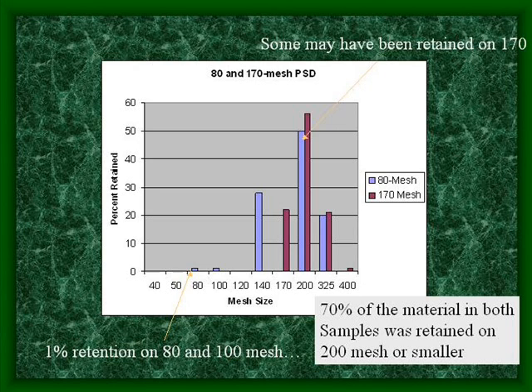Here's a comparison of the particle size distribution of these samples. Both of the samples were quite similar. 70% of the material in both were retained on 200 mesh or smaller. The only difference is 1% was retained on 80 and 100 mesh in the 80 mesh specimen.